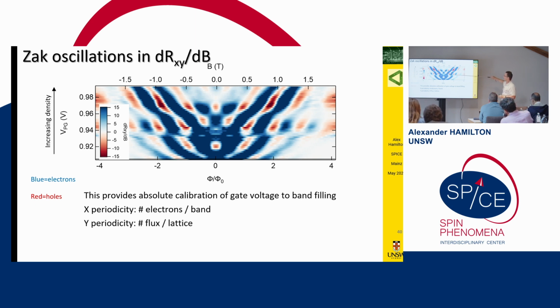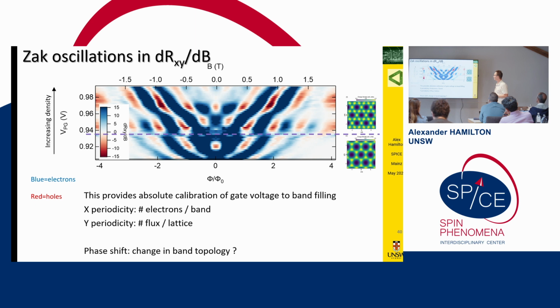So that's this periodicity. So I've got an absolute measure between my electrical gate voltage that I'm applying and the number of bands I've filled. So I know exactly where I am at any point on the band structure. And then what you see in the oscillations is there's this kind of phase shift here, and that just seems to happen at the same point as we go from a honeycomb lattice down here to a Kagome lattice up here. We don't quite understand why there's a phase shift, but it doesn't appear in single particle calculations, but there you go.